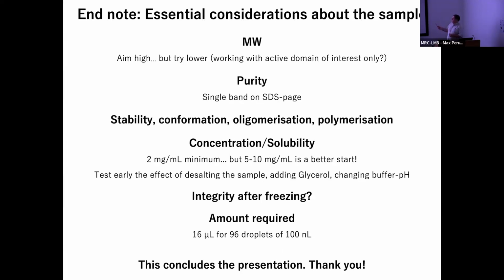And there are also reasons why a highly salty sample is not going to crystallize, but that's one main reason. Another simple thing, the effect of glycerol. A bit of glycerol can make a big difference. Too much glycerol is a bit the same problem as too much salt. But if you didn't have glycerol, you could run in parallel a sample with and without glycerol, let's say at 10%. A big factor, which is also relatively easy to check first, is the pH. We have a pH screen actually, so you could just set up a plate with only buffers and look at it the same way as you look at drops for crystallization, to see where your protein is happy or not. That's a simple way to check different buffers.